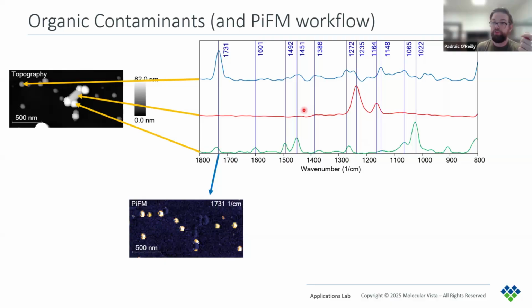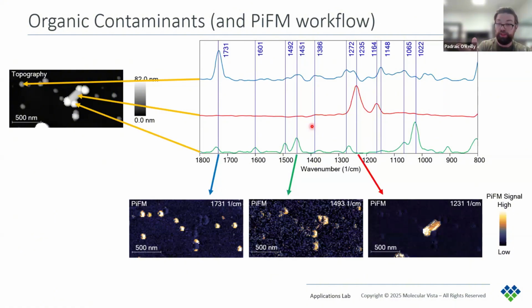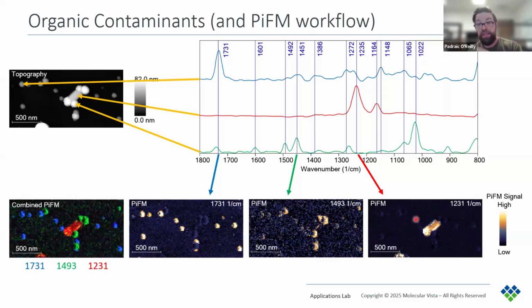Then we can go ahead and choose wave numbers that are stronger for these materials and map those, which is what we see here with these two. And we can go ahead and then combine these images. And now we see that every particle that was in the topography image is highlighted in the combined image. So this means that we have very likely identified all of the components in this area. But of course, again, you can confirm by taking more spectra.